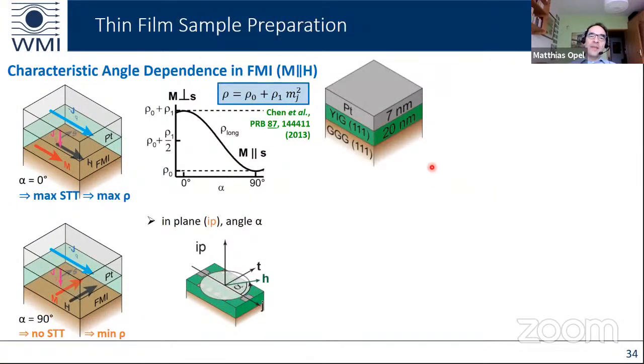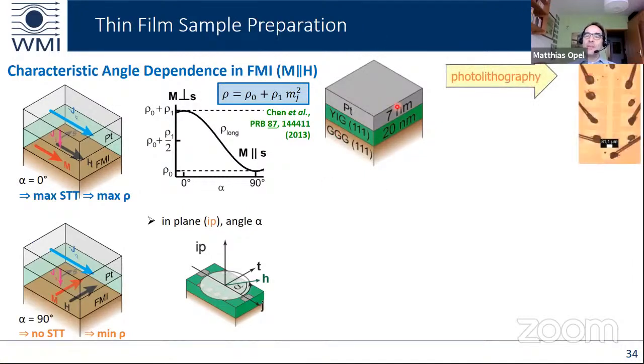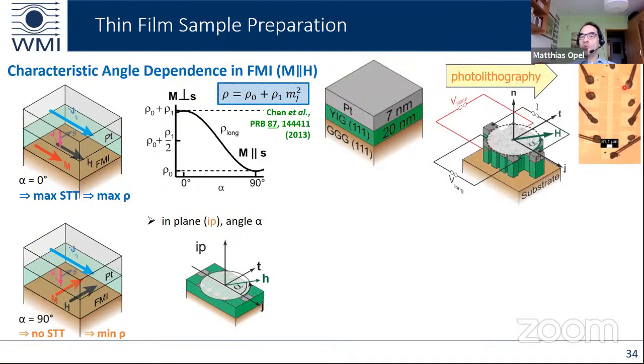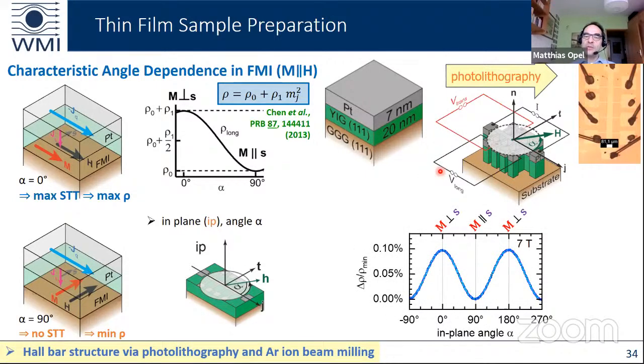So what we do is we apply the magnetic field to our sample. We pattern the sample to a Hall bar geometry and apply an electrical current. Then we rotate the magnetic field and we measure the longitudinal and the transverse voltage and resistivity. I just want to show you the longitudinal voltage and the longitudinal resistivity, and then we see this characteristic angle dependence.